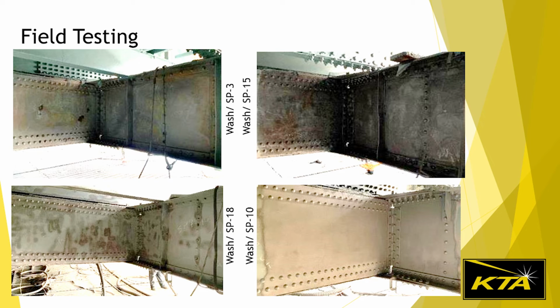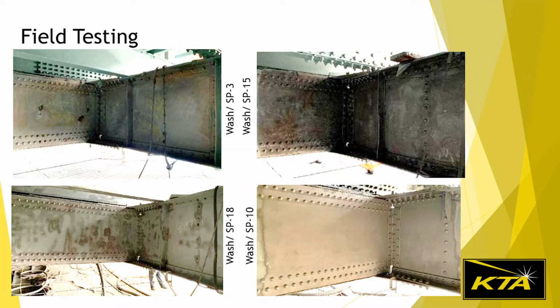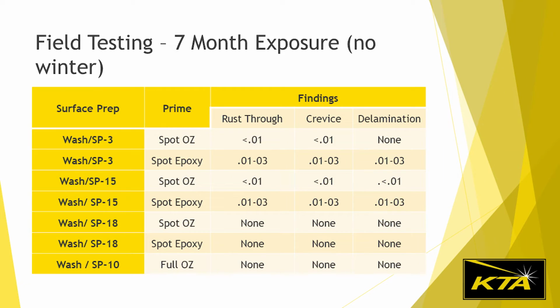The field test cleaning and painting on the actual structure was done in March of 21. There were 7 areas of the bridge that were prepped and coated. Each area was approximately 100 square feet and was located along the floor truss lower chords. One side was prepared per surface prep method, coated with a spot epoxy prime coat, and then the back side was prepared with a spot organic prime coat. The only exception is the SP10 clean surface was only performed on one side and received a full organic zinc primer coat.